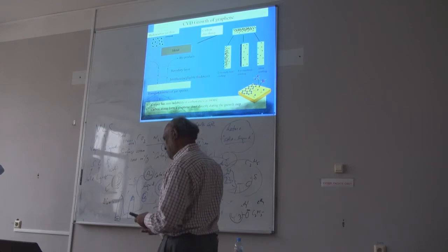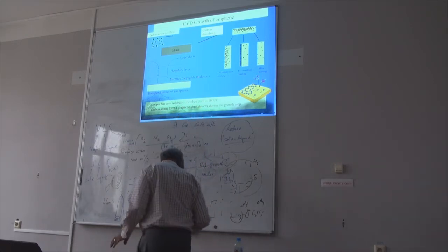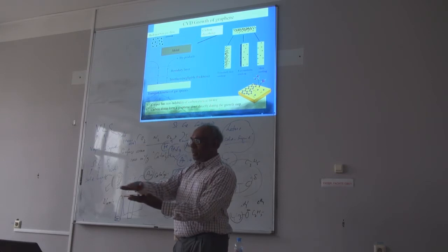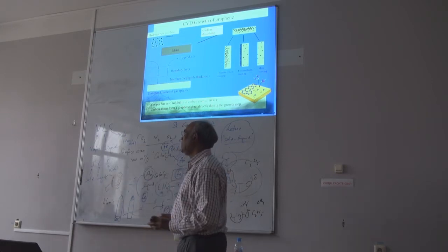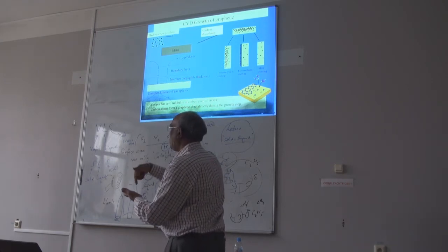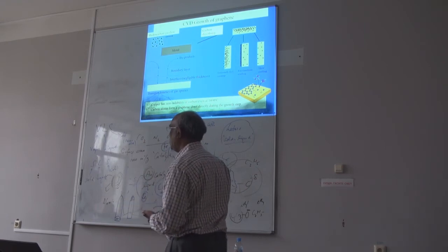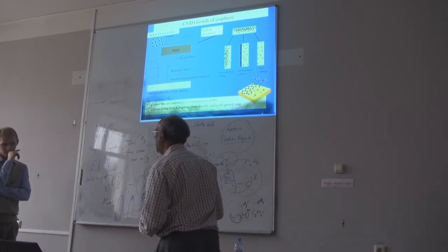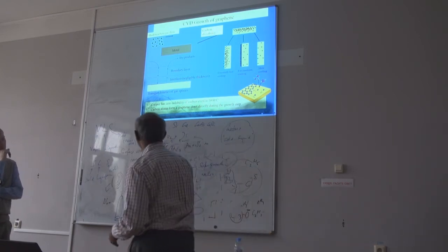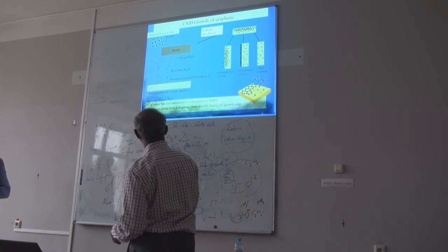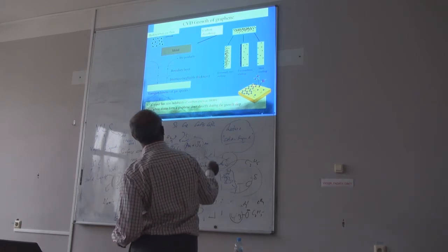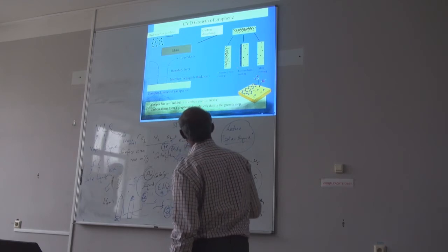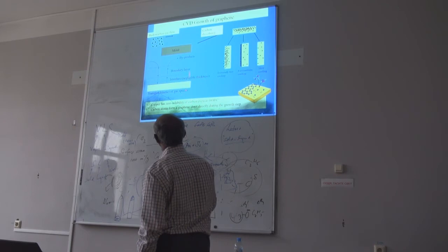So if you use copper, yes. Copper, это медь. If you use a simple copper foil, like if this is my copper foil, after growth you find graphene covering the entire copper foil, because nothing is going into the copper, because carbon and copper solubility is very low. If you use iron, they dissolve and eventually grow like tubes. But in this case, because of zero solubility, this is the important thing, carbon atoms directly grow on the surface. If something goes in, that will again come out and collect on the surface.